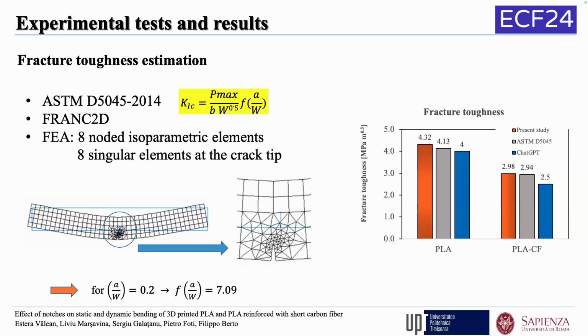So inspired by the presentation yesterday of Francesco Iacoviello, I would like to check what ChatGPT gives for these materials. And you can see, asking for the fracture toughness of PLA, simple PLA, I got 2 megapascal square meter. Defining more, PLA 100% infill and with contours, the result of ChatGPT is 4 megapascal square meter, quite close to what we get experimentally. Also for the reinforced material it gave us 2.5 and the test result is 2.9. I don't know. Maybe in future the predictions will be better. However, in my opinion, we should stick to performing tests.